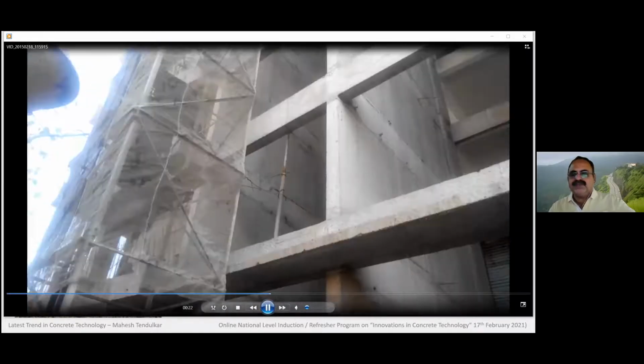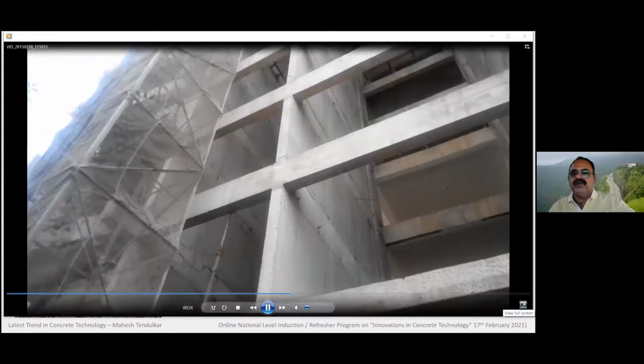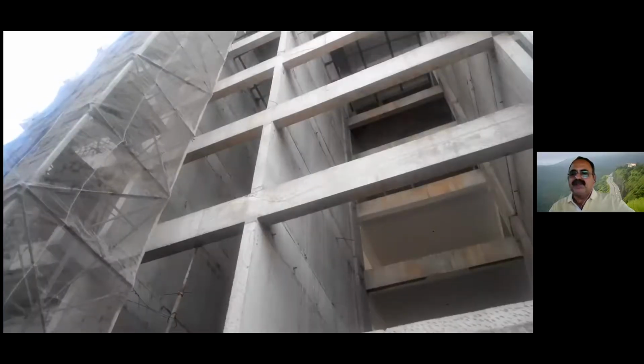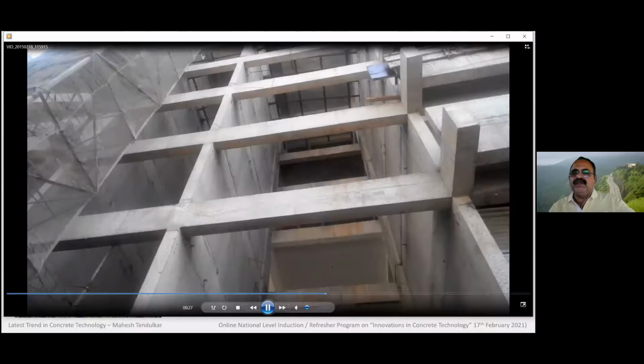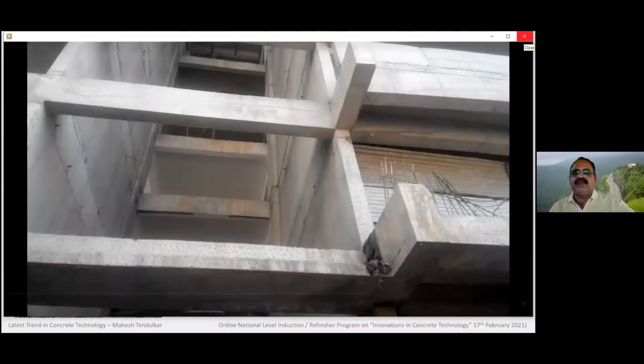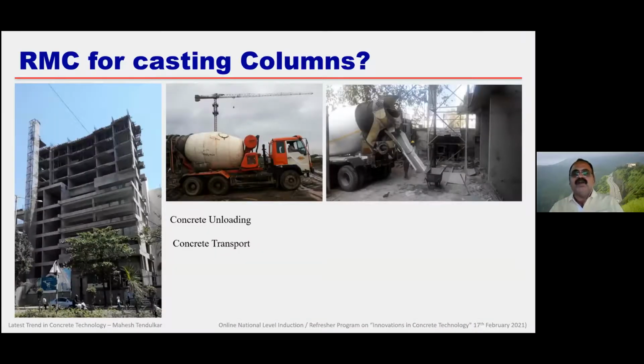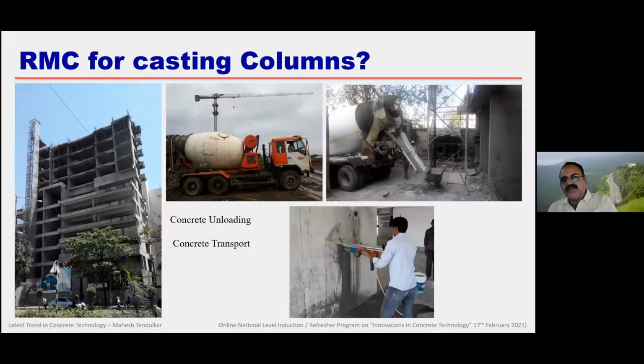So obviously such transit mixers cannot be unloaded within 3 hours, which is a very large time. So by that time our concrete will get a problem. When we tested the concrete, we took the core from that particular slab, because obviously if there is a drop in workability, the transit mixer driver will not tell you, he will simply add water and unload the concrete.